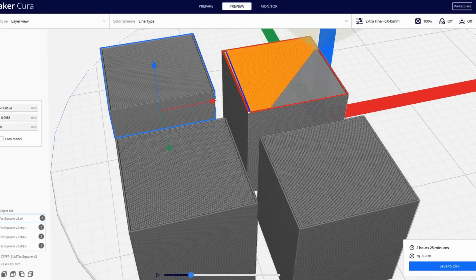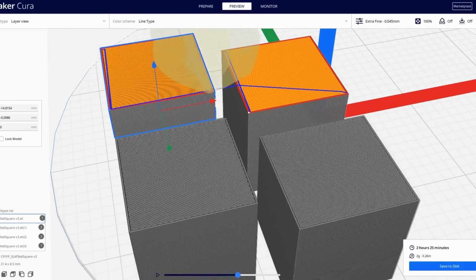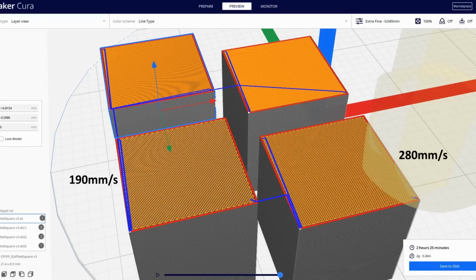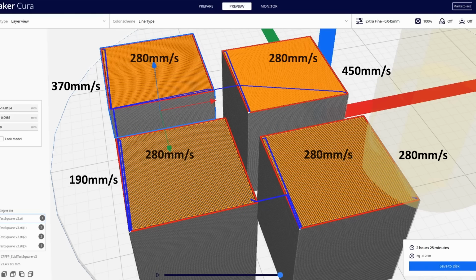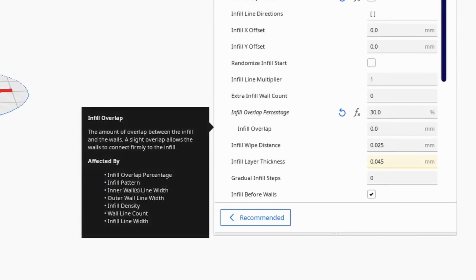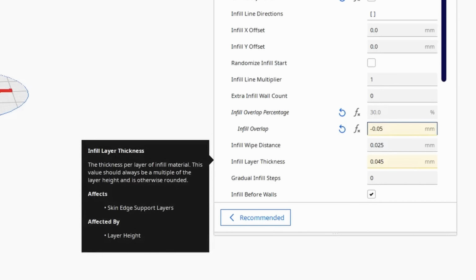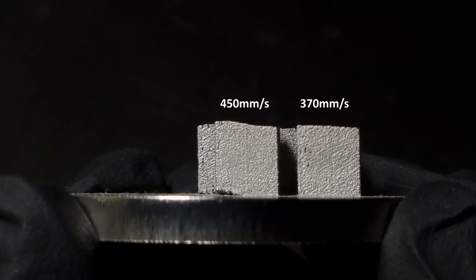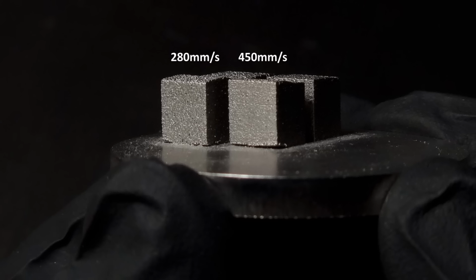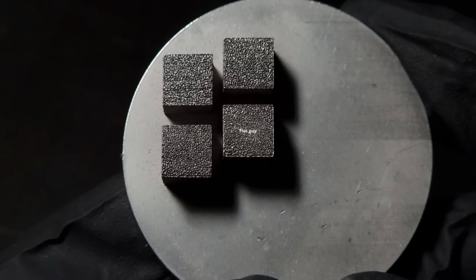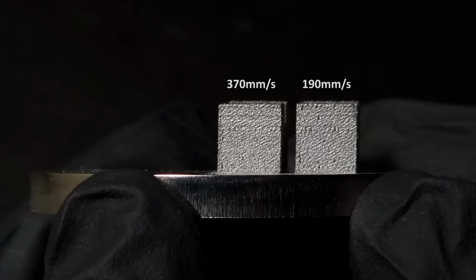Problems aside, I set up another run to see if I could improve the surface finish. For this run I performed 4 tests with wall speeds of 190, 280, 370 and 450mm per second, a fixed infill speed of 280mm per second, and various hatch spacings ranging from 50 to 125 micrometers. I also decreased the inset of the infill from 0 to -50 micrometers, just to ensure no overlap would contribute to raised walls. It's pretty clear that of the 4 cubes, the surface finish was the best on the cube that was printed with the fastest walls and the shortest hatch spacing, with the appearance gradually degrading at slower speeds and broader spacings.